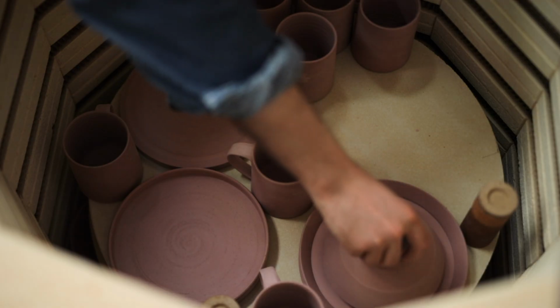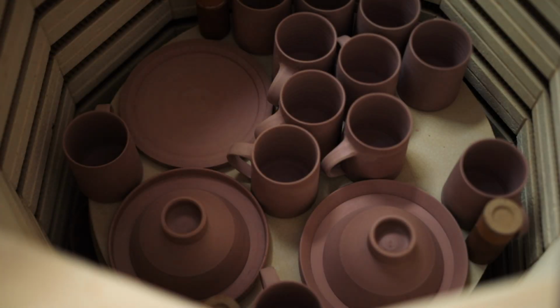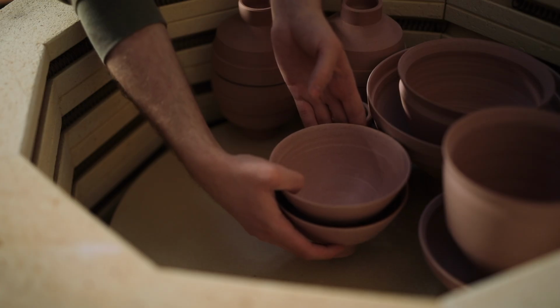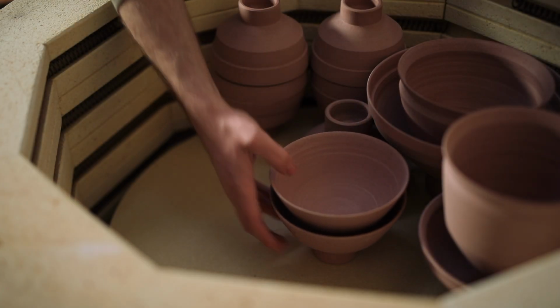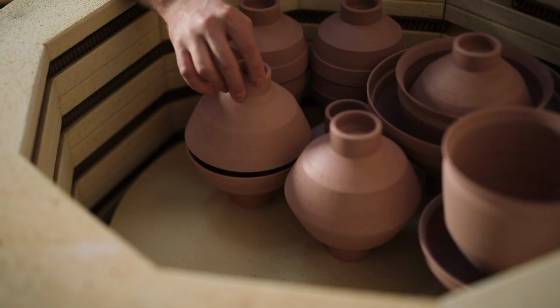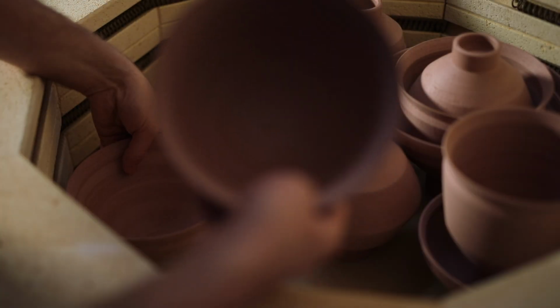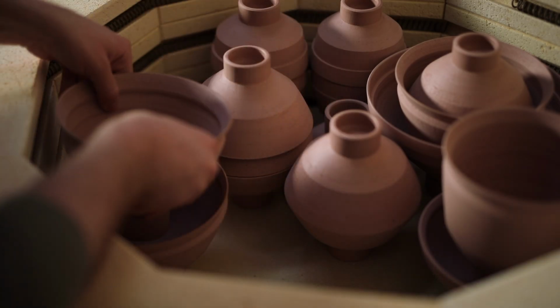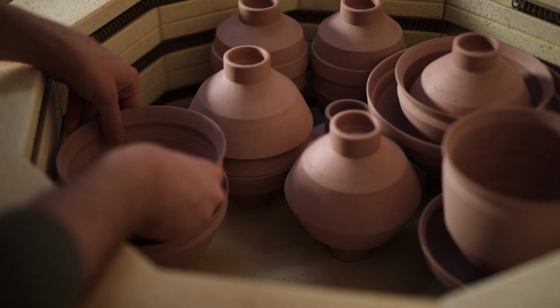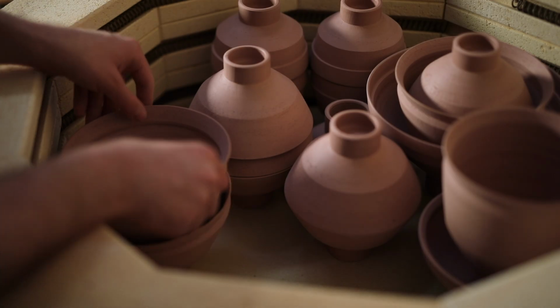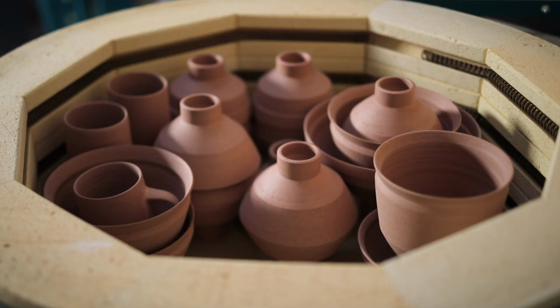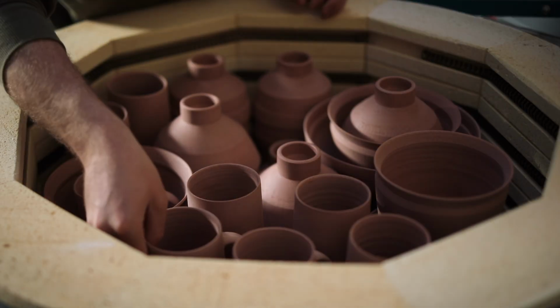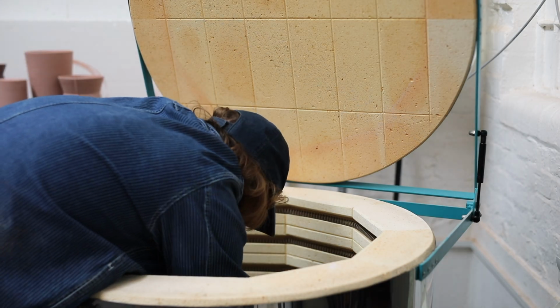The next thing I'll do with these bowls is dry them really slowly to bone dry. Once they've turned bone dry, they can be placed into my electric kiln for a bisque firing to 1000 degrees Celsius. And for this firing, as the clay won't get hot enough to stick, the pieces can be stacked and piled up as densely as possible, which I do to make each firing as cost effective as it can be. This first firing chemically changes clay into ceramic, partly fusing the particles that make up these pieces. And it's for this reason that the pots will no longer disintegrate if placed in water, as they will sort of become linked.